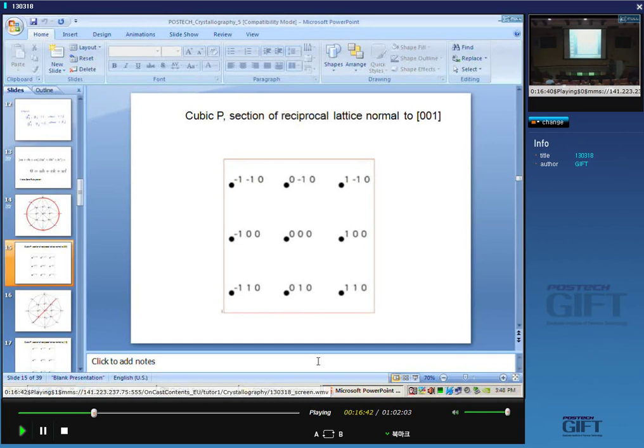So this is the reciprocal lattice section, just like if we are looking at a real lattice, we have lattice points. These are reciprocal lattice points. And each vector on here is at 90 degrees to the plane, and its magnitude is 1 upon the spacing of those planes. Okay? So this vector here, for example, is the normal to the 1 bar 1 0 plane, and its magnitude will be 1 upon the spacing of those planes.